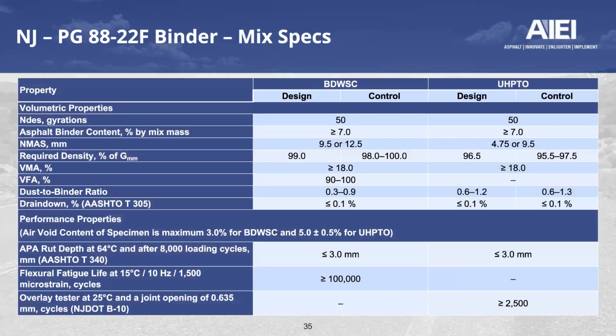If we look at the mix design, whether it is the ultra-thin performance overlays or the bridge deck waterproofing overlays, you're going to find that they're designing these on a gyratory compactor with 50 gyrations. The asphalt binder content is intended to be very high at a minimum of 7%. They do have specifications for the bridge decks of 9.5 as well as 12.5 millimeter mixes. For the ultra thin toppings, they have 4.75 as well as the 9.5 millimeter mixes.